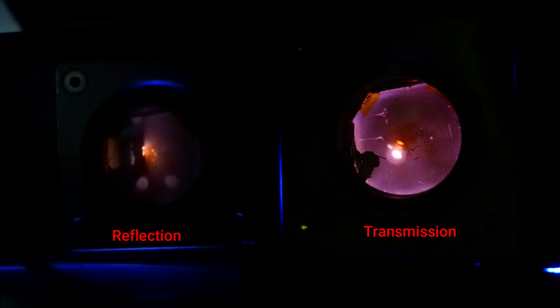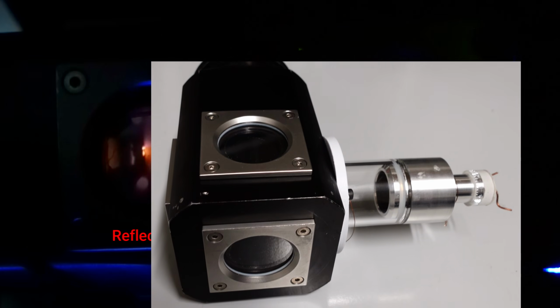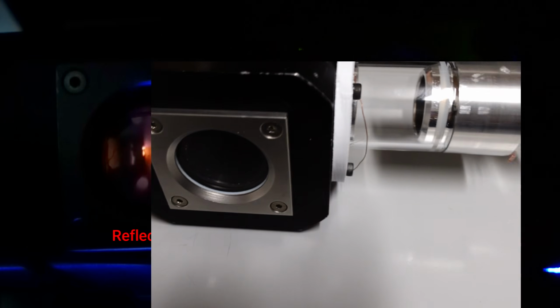So in conclusion, we have seen these two types of electron diffraction. The data are promising, but further experiments should be carried out to get higher quality images. The reflection setup would require a better sample holder to allow the choice of the incident angle, while for the transmission experiment other substances should be tried. Furthermore, both experiments are limited by the low amount of space between the diffracting sample and the detector. A greater length would allow for collection of a bigger image, and so allow us to distinguish better the zones of higher and lower electron intensity.